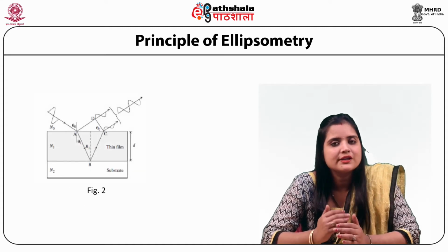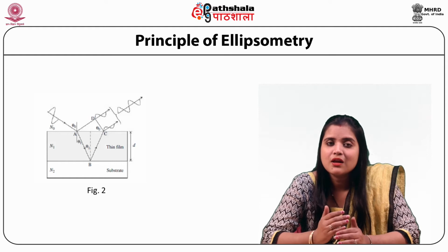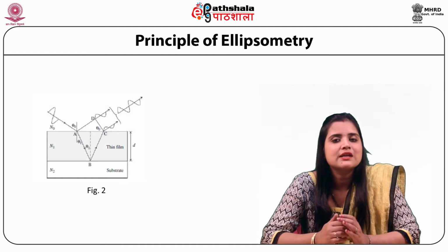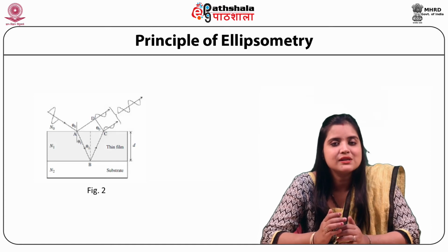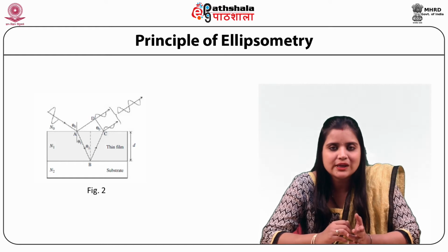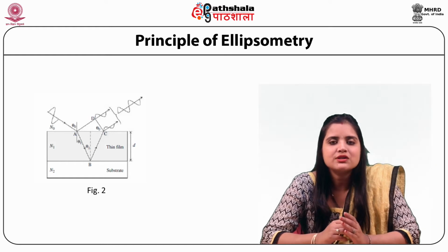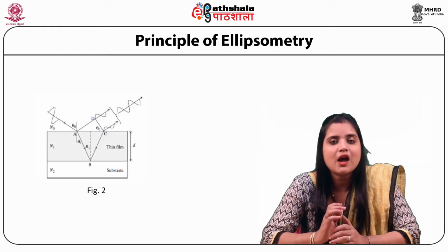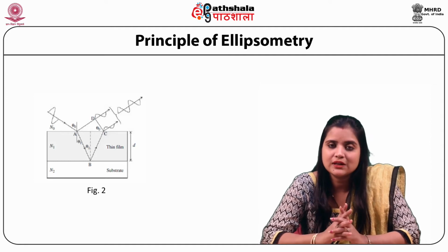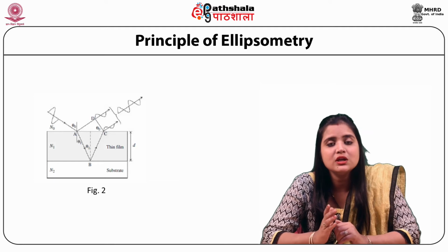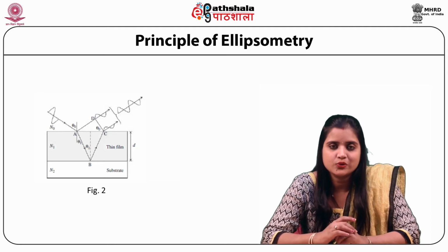If there is absorption, then the refractive index can be a complex quantity. Hence, the angles in general are complex. In the present case, the system has three layers having refractive index N0, N1 and N2. First and third layers are separated by a second layer having thickness d as shown in figure 2.